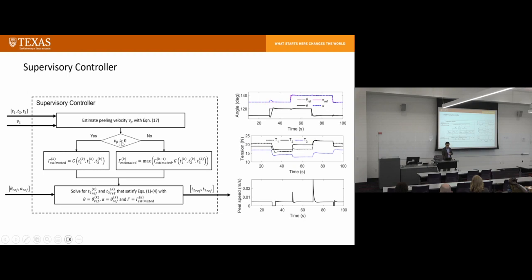So we estimate peeling velocity. If the peeling velocity is greater than 0, then we can update our adhesive energy estimation using the energy release rate. If it's not, then we have an algorithm to estimate the adhesion energy. And then we solve for the tensions we need to follow this reference angle. This supervisory controller works very well, so we can have our tensions determined, and we send them to the lower-level regulators, which are PID controllers. The simulation result shows that if you have a desired peeling angle, theta and alpha, then we can control tensions. By following this tension control, we can have the desired angle following.